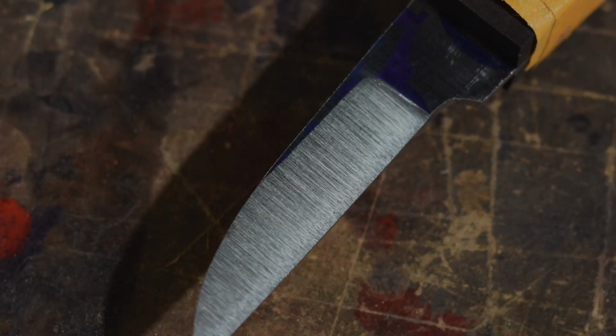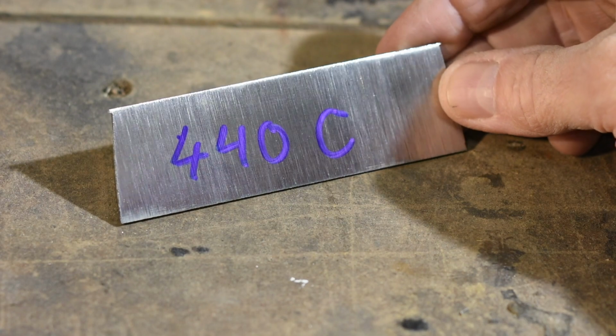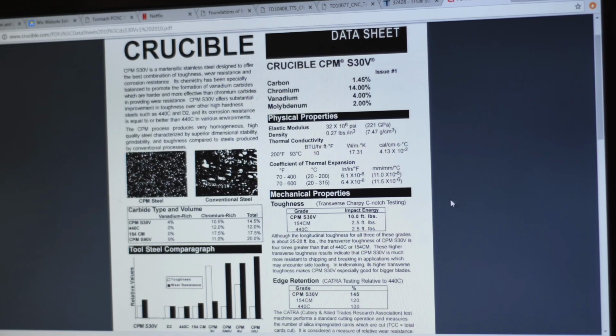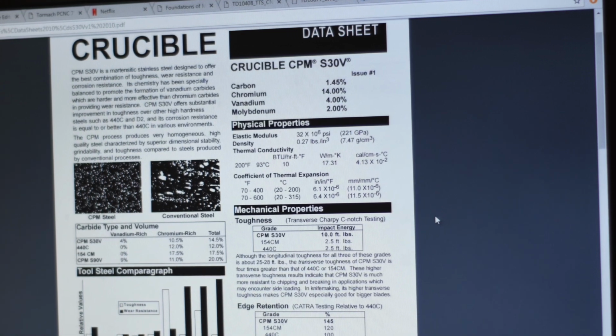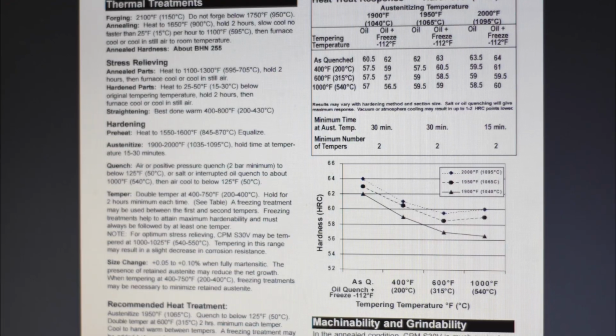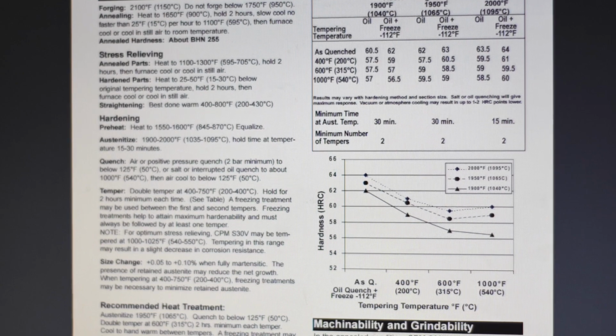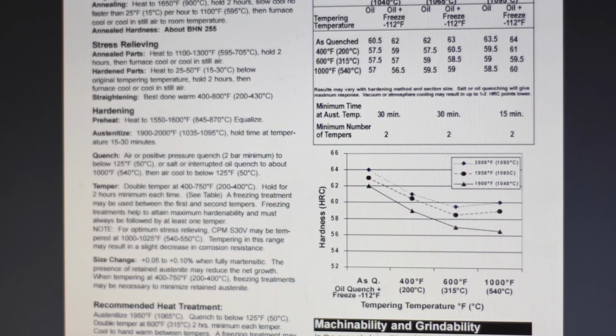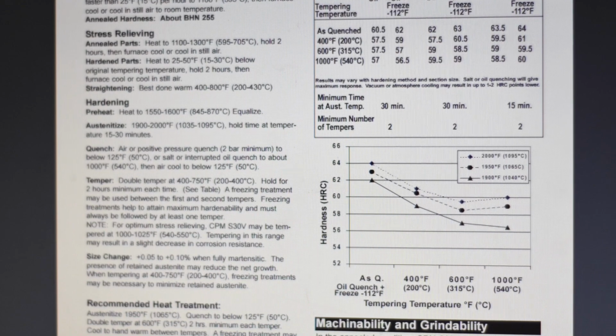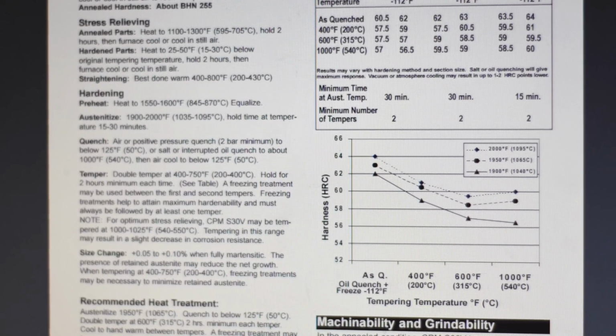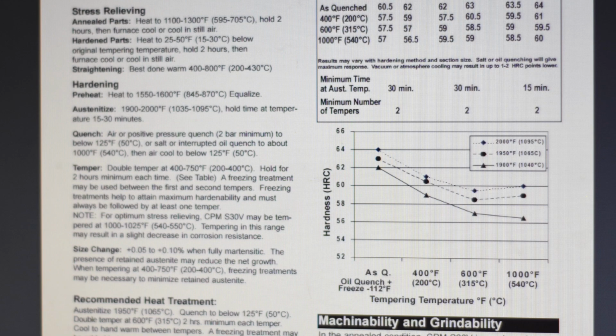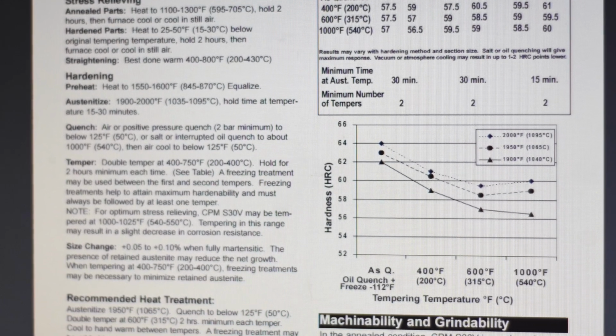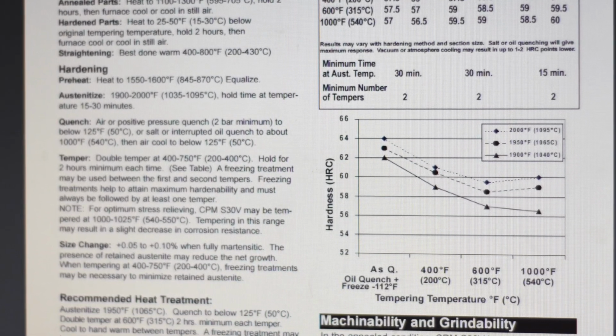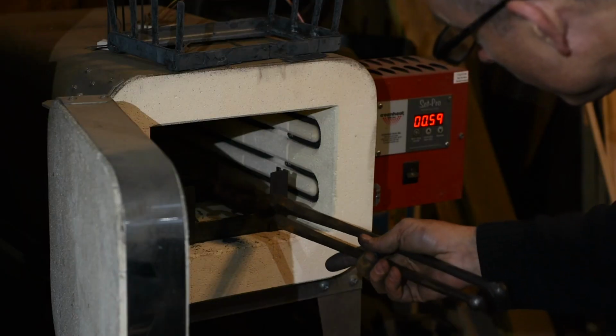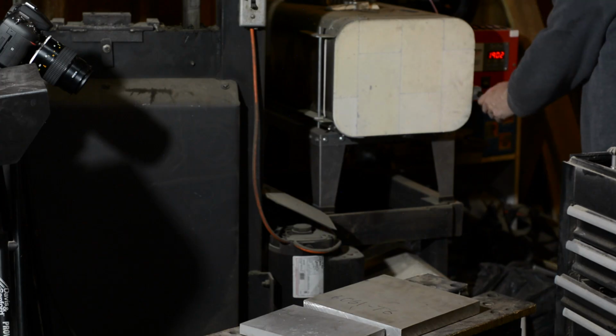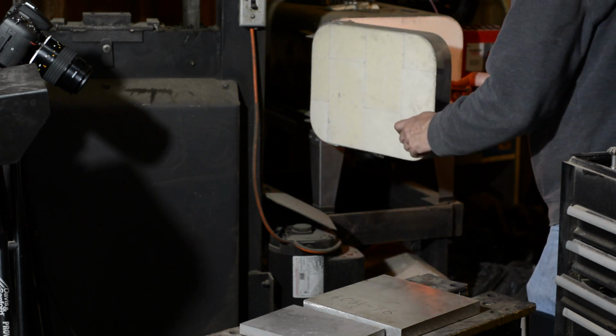Time for heat treating. Virtually all steels that are capable of being hardened will have heat treating recipes available from manufacturers of the steel. These are found in the form of technical data sheets. In some cases, they may take a little decoding. A technical data sheet may refer to the austenitizing temperature. That's how hot the steel needs to be heated before being quenched. They'll also sometimes refer to soak times. The soak time is how long you leave it in the heat treating oven at a particular temperature. In this case, I'll be heating the steel to 1900 degrees Fahrenheit and soaking it for 30 minutes.